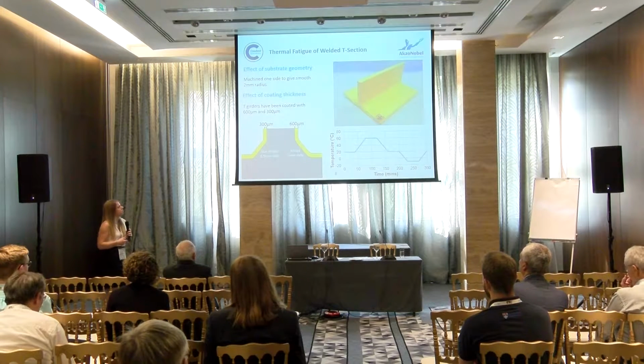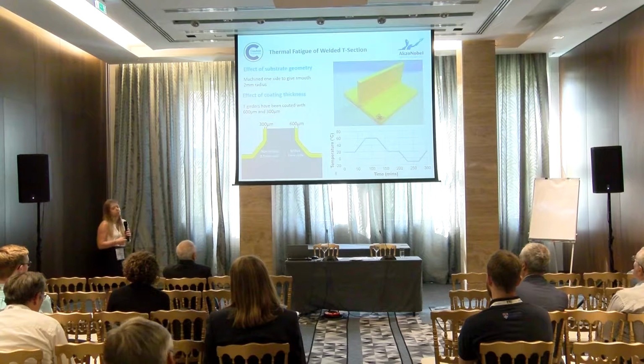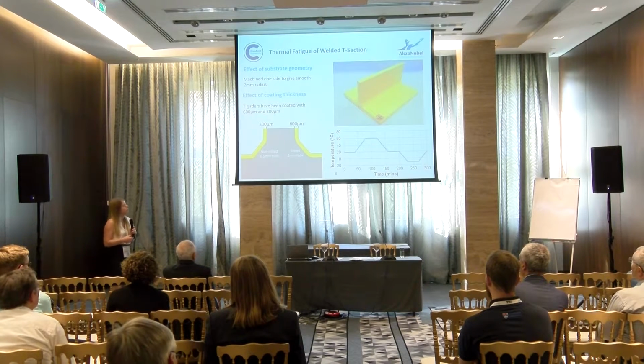So once the steel was welded and milled, it was grit blasted and spray coated. 5 samples were spray coated with a 600 micron dry film thickness, and 2 samples were spray coated with a 300 micron dry film thickness. All of the samples were then placed in an environmental cabinet and subjected to the following thermal profile.